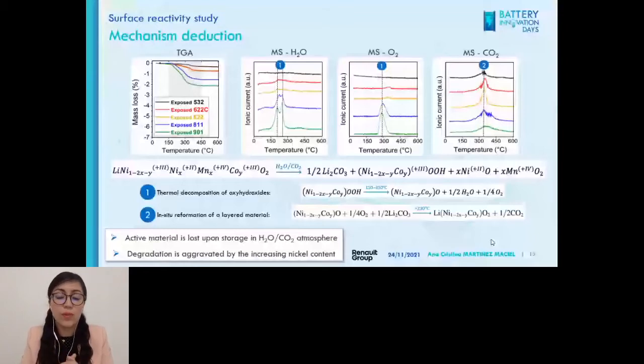So we propose that at the surface of NMC, we are producing lithium carbonate, an oxyhydroxide of nickel and cobalt, and oxides of nickel and manganese. We support this reaction on the fact that reaction number 1 here says that the oxyhydroxides will decompose into oxides, water, and oxygen, which is exactly what we see in the graphs—water and oxygen.